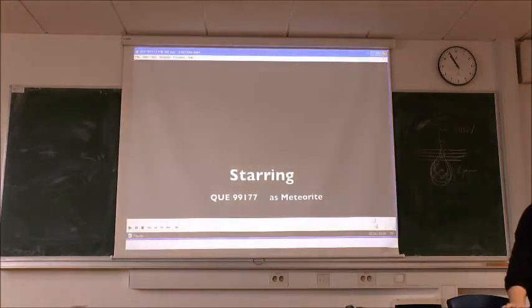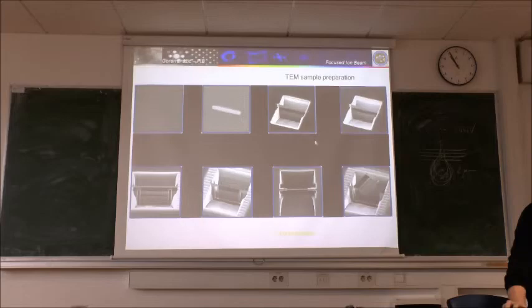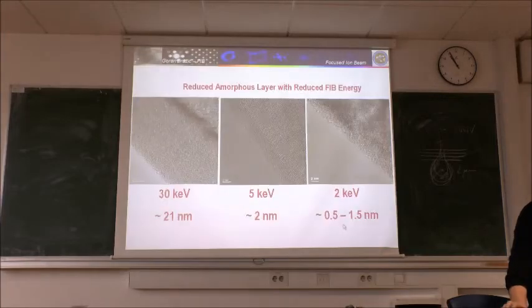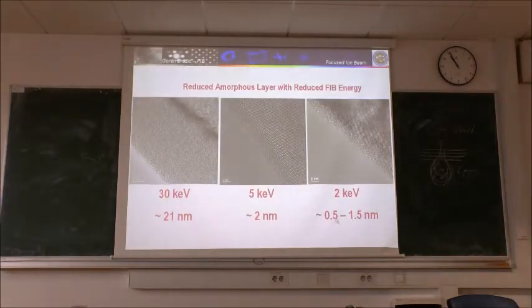Okay, but of course the producers of FIB say, no problem, 1 hour, 2 hours. Overnight you can do 5 to 10 samples. Then you speak with the guys that are really doing FIB, that are preparing samples, and they say, okay, if you prepare 1 good lamella per day, you're really experienced.